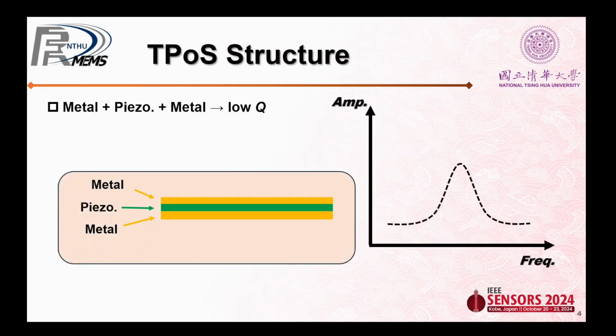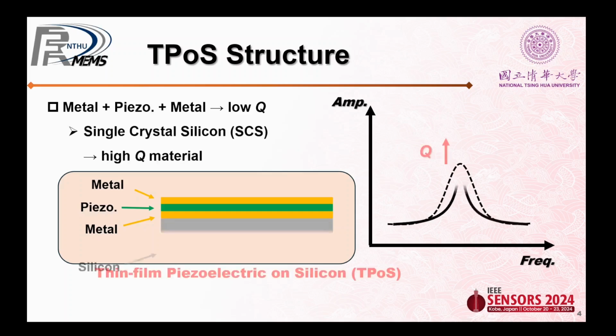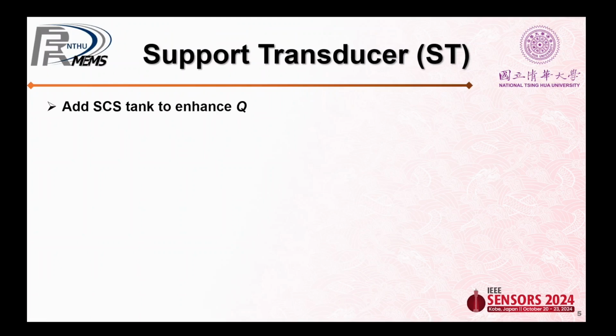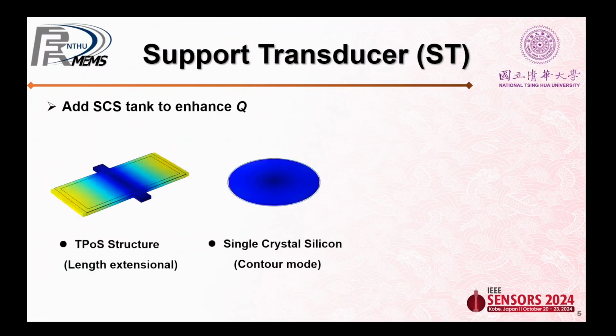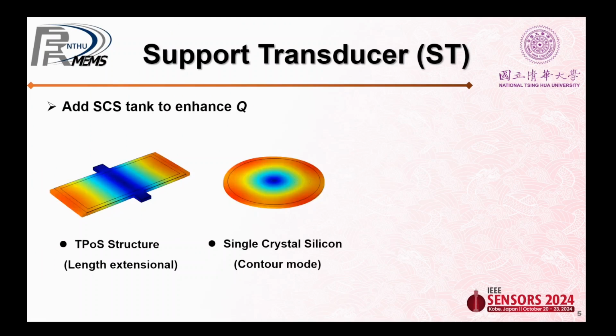A typical piezoelectric resonator consists of 3 layers: metal, piezoelectric material, and metal. This kind of structure tends to suffer from a low quality factor. However, adding a layer of single crystal silicon beneath the structure, known as the TPoS structure, can enhance the quality factor due to the material property. Additionally, we introduce another approach called the support transducer to further enhance the quality factor.